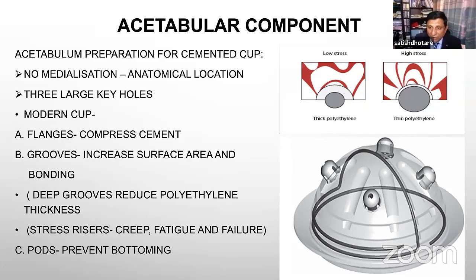And there is further evolution in the modern cup, like we do have flanges. The flanges help to pressurize the cement equally, and to compress the cement all around the socket. The grooves increase the surface area and binding to the cement. However, deeply increased grooves can reduce the thickness of the plastic or polyethylene, and that will lead to increased stress, leading to early failure. And the pods are to prevent the bottoming out of the cup. So basically, it will help to have an equal cement mantle all around the cup, which is very important for the stability of the cemented cup.